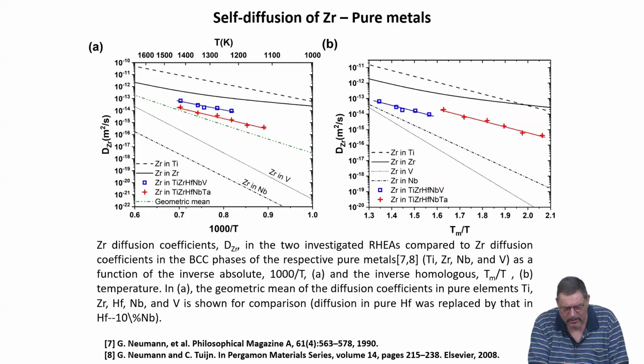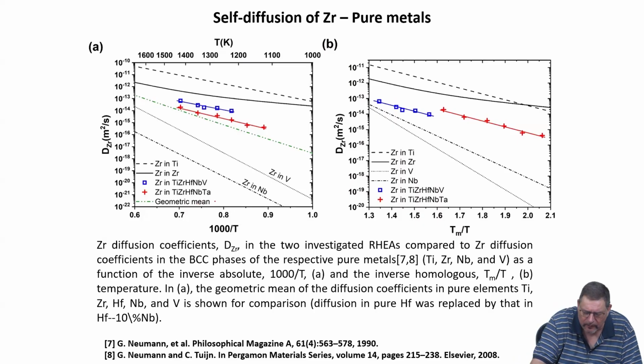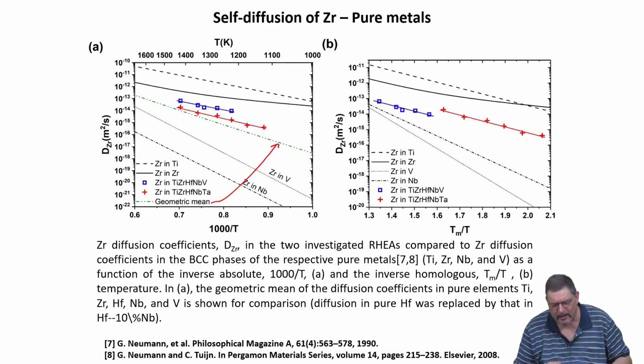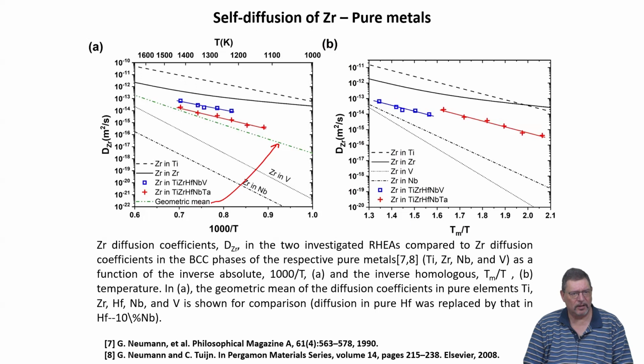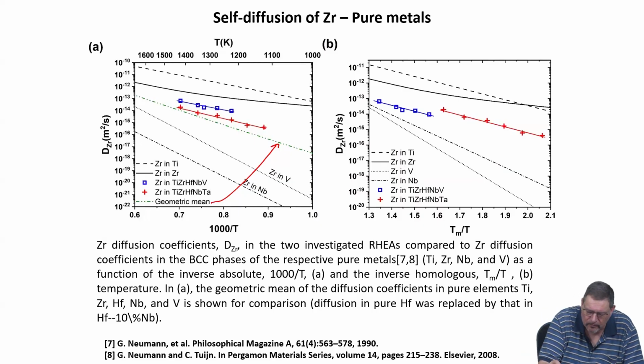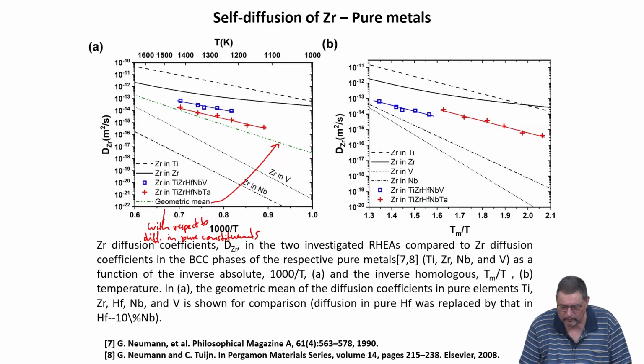And this is basically then the geometric mean, the green curve here. So this would mean this is the value you would expect if you calculate just the geometric mean for zirconium diffusion in these refractory high entropy systems based on the diffusivity of zirconium in each pure constituent. And then basically you again see this as a comparison on the homologous scale as well as on the absolute temperature scale.